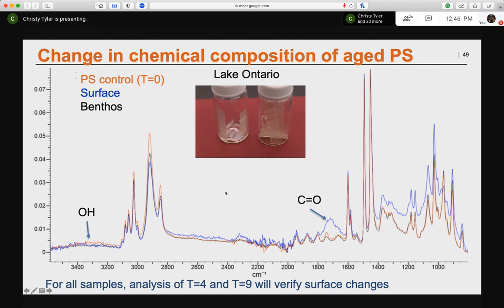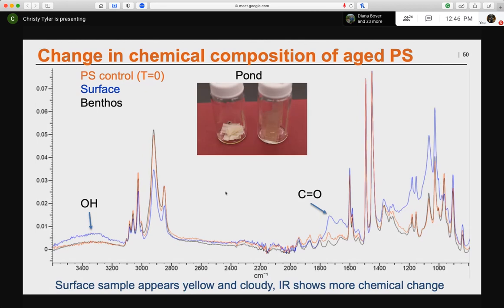Moving on now to the pond. So this is that rural pond down near Naples. We're starting to see some actually very large changes. And if we look again, this is more so at the surface than the benthos. In that picture, you can see that the sample from the surface was very much yellowed, very much clouded. So really this oxidation, whereas the one down at the benthos was not as affected. And like I said, in terms of the spectra, it's almost identical to before being deployed. So these chemical changes are very dependent on location, both within the water column and also spatially where they're at.